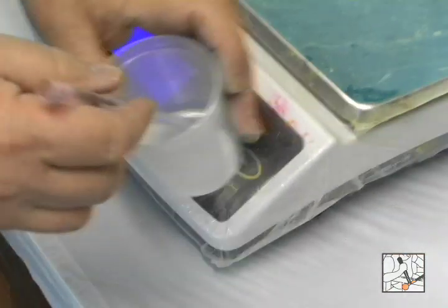If you look through that, it's very cloudy. But as you continue to stir, with anything behind that is readable, it will become more and more transparent and less oil and water kind of look. You're beginning to be able to see that reading, that writing through there. Making sure you're scraping the sides of the cup. You don't want any areas where there's nothing mixed.